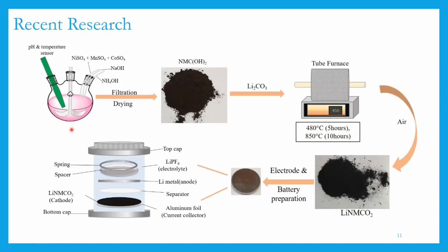This is a schematic of the process to prepare this material for electrochemical testing. You start with the co-precipitation. You have your metal ion solution, your pH adjuster, which is sodium hydroxide, and then the ammonium hydroxide, which is your chelating agent. After you get this material, you filter it, and then you dry it.